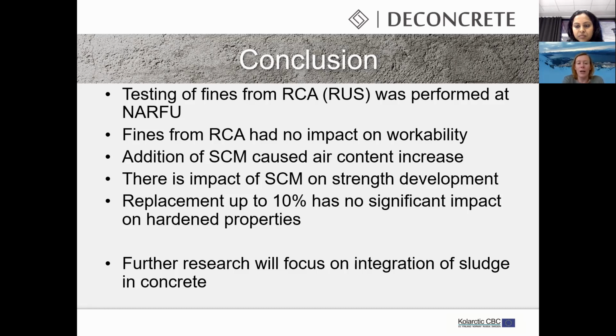So we can see that the fines from recycled concrete aggregates don't have a significant impact on the workability, while the fines from sludge reduce the workability, which has to be compensated by the addition of superplasticizer. There was a visible inclusion of air when the supplementary cementitious materials were added, and therefore we controlled it with the air entrainer. And the same actually might occur with the concrete production. Therefore, we need to keep in mind that there might be such an effect.